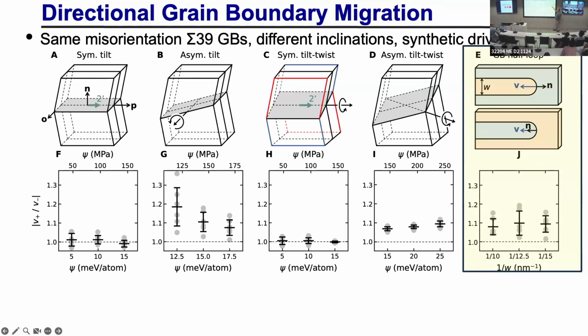Now, in this case, I've just taken the two crystals. I put the yellow one on the outside and the blue one on the inside. So basically, I just switched the direction of the normal of the grain boundary. I've just switched the blue and the yellow crystals. And again, in this case, where the driving force is curvature, capillarity, you see that the migration velocities are different in the two directions.